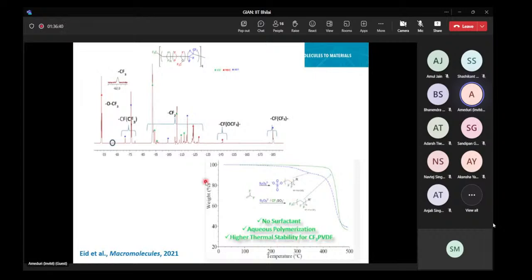And when you look at the thermal stability of the copolymers bearing a CF3 end group, this is here, very stable, compared to that prepared in the presence of a persulfate, in which you have a sulfate end group. You can see that you have a decomposition here because you have a depolymerization starting from the end group, in this case at a lower temperature, while the presence of CF3 does not allow this depolymerization. So this is what is called the unzipping depolymerization system. What was interesting is that we worked in water, we didn't use any surfactant, and we had a very good thermal stability compared to conventional polymerization of monomer in the presence of persulfate.